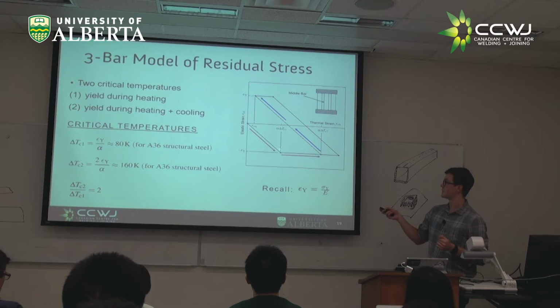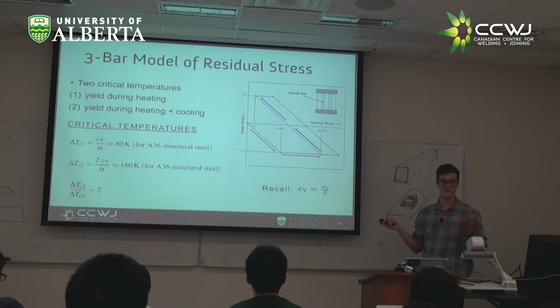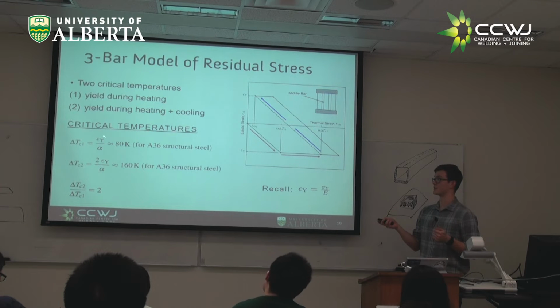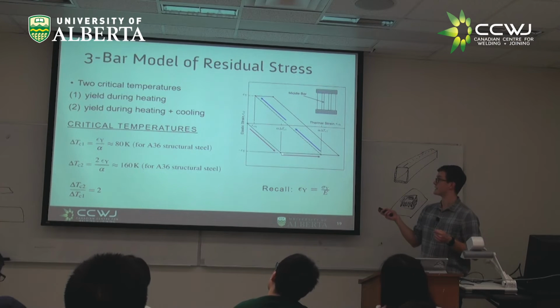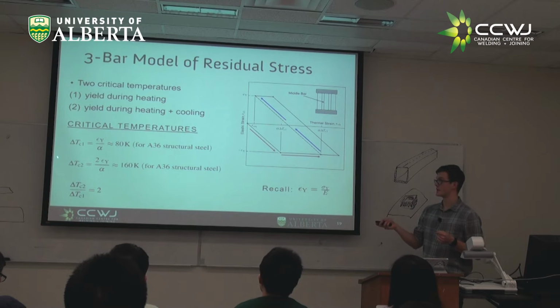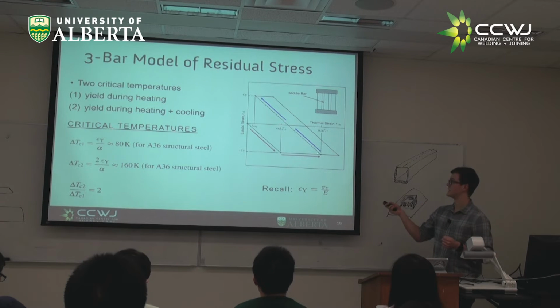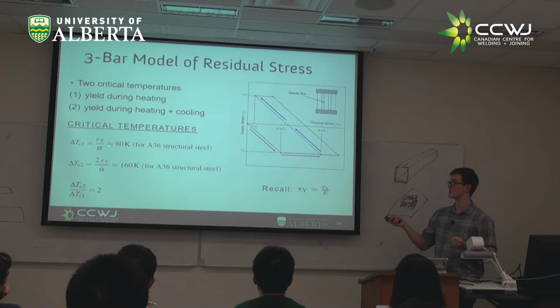So really, if we have those two critical points, and we look at them not as a thermal strain, but now as a temperature, if we assume we have a constant coefficient of thermal expansion alpha, our thermal strain is going to be proportional to whatever that strain is at this point, divided by alpha. We can define two temperatures. And we're going to call this TC1 and TC2. And these are the two critical temperatures we worry about for residual stress. And we can see that if we look at this point, this thermal strain here is simply going to be equal to our yield strain. So we can divide our yield strain, which is going to just be our yield stress divided by elastic modulus. If we divide that by alpha, we can calculate what this temperature is.